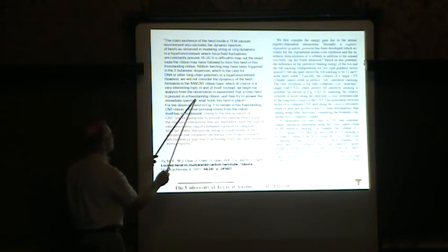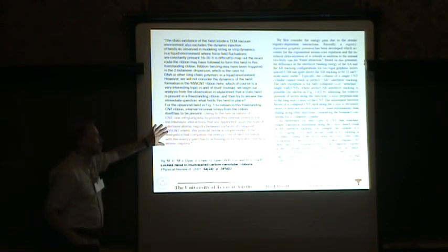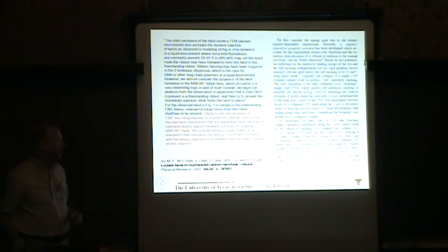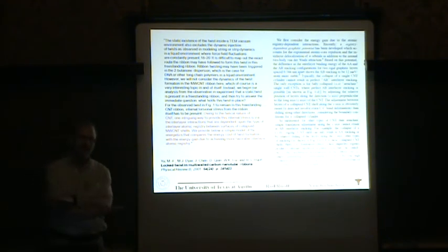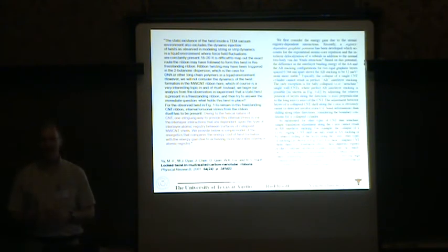So this is a description of how the ribbon might have twisted and why there could conceivably be this static twist in a freestanding ribbon. And so we said it could actually be the interlayer interactions. So in many cases, you can ignore the interlayer interactions and just smear it out and assume that the atoms are not there. You don't have to worry about atomistics in a sense. But in this particular case, we're saying that it's actually critically important for the overall structure that's observed.